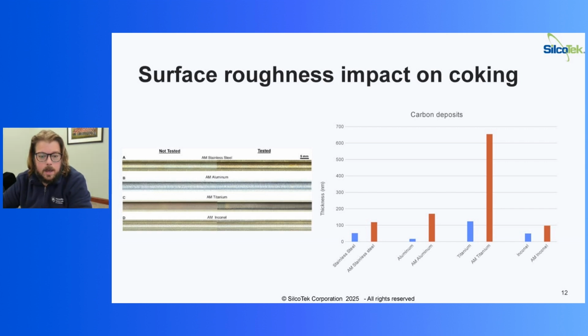And sure enough, here looking at these 3 different tube materials, you can see whenever they did the 3D printed tube and they did the exact same study with 215 degrees C, sending the jet fuel through the tubes and seeing what deposits on the other end. If you look at the thickness of the carbon deposits, every single additively manufactured tube is worse than the typical standard tube material that you would just buy out of the package. Titanium was dramatically worse, aluminum very much worse as well. Inconel was the closest to the drawn material, but they were all just worse as far as the thickness of the carbon deposit that occurred on them.